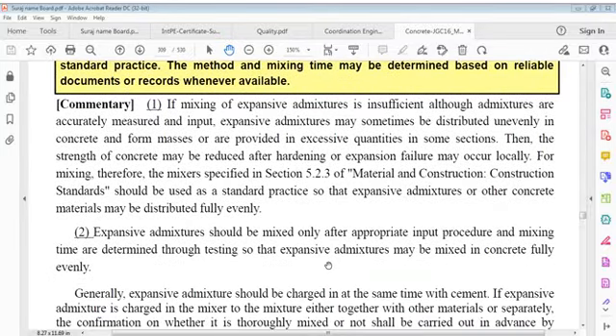If mixing of expansive admixture is insufficient, although admixtures are accurately measured and input, expansive admixtures may sometimes be distributed unevenly in concrete and form masses, or are provided in excessive quantities in some sections. Strength of concrete may be reduced after hardening, or expansion failure may occur locally. For mixing, therefore, mixers specified in materials and construction standards should be used as a standard practice so that expansive admixtures or other concrete materials may be distributed fully evenly.